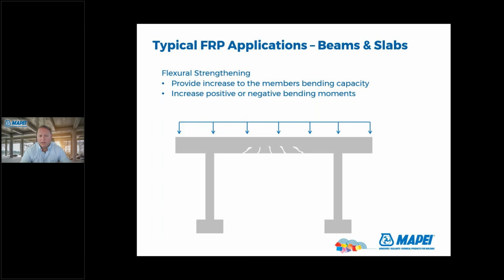So some typical applications for flexural strengthening. If you have a uniform load here on the top, you want to increase the bending capacity. On the bottom of this beam, the fibers on the concrete there are going to be at the most extreme tension phase. And so in a situation like that, you put the FRP there. But then think about the top, on these areas above the column. If you add a load, it's going to want to sag the opposite way. And so FRP would go on the top. And so you can utilize FRP to address your positive and your negative bending moments.